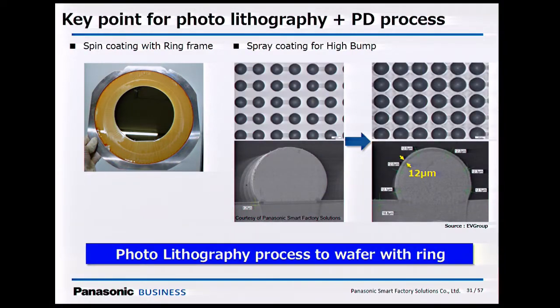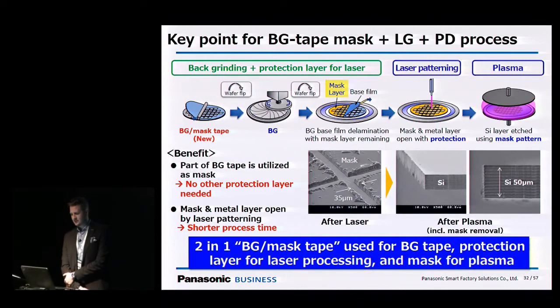For photolithography, we either apply that with a spin coating on a ring frame or spray coating. I'll show some examples of that at the end of my presentation. And then this is the alternative with laser patterning. One of the possibilities is a tape from the Furukawa company in Japan, which combines backgrinding tape and a mask layer in the same tape. I will show a video about it, but when you remove the backgrinding tape, it leaves this yellow mask layer, which is then patterned, and after that it's the same principle as a photolithography mask. Where there's no mask, it would be etched.